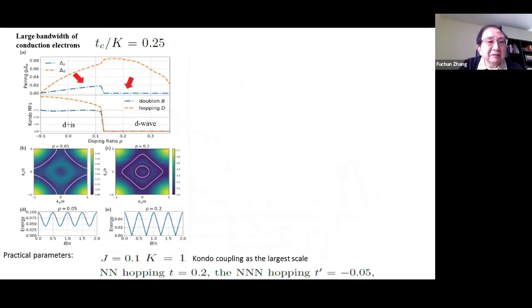And this is the main result I show you, okay. So for certain parameters like tc, the hopping integral of the conducting electron, versus the K, or Kondo coupling, equal to a quarter. What I want to emphasize is this is a pairing multiplied by this gt, the renormalized factor, such that at no doping, there's no pairing, okay. So it's different from the mean field pairing, just multiplied by an additional renormalized factor. And I have decomposed the pairing in terms of the S wave part, the blue ones, and the dashed ones, it's D wave, like this, okay.